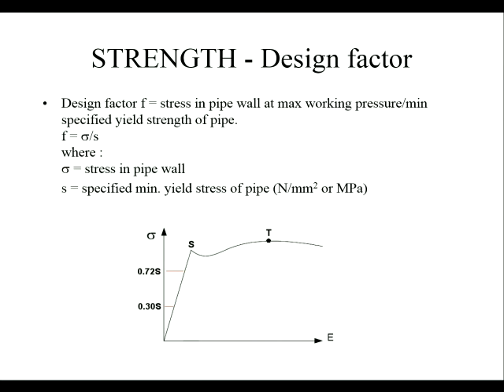And then we multiply that by some factor, or in this case we're dividing by a factor just to say what we would want. So the stress in the pipe wall sigma then has to be reduced, or has to be increased to get up to the yield stress. So way of looking at that, we've got the stress strain curve here, S. This one's got the yield drop, so it's an old steel. We can see that the yield stress is marked there, but we would actually design at a fraction of that, 0.72S or 0.3S, you can see there. So those would be the design limits for the stresses in that particular material, and it's less. And if we do that, everything should be in the elastic range, and we always design with things in the elastic range.